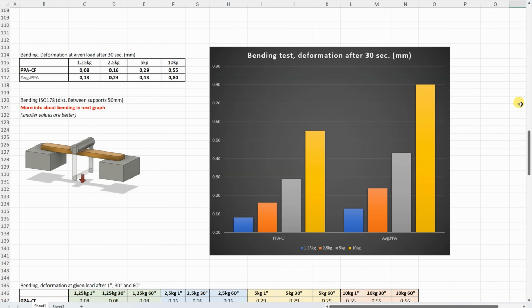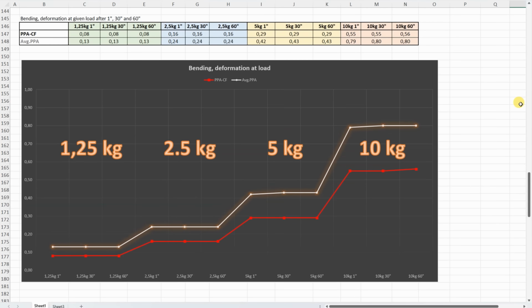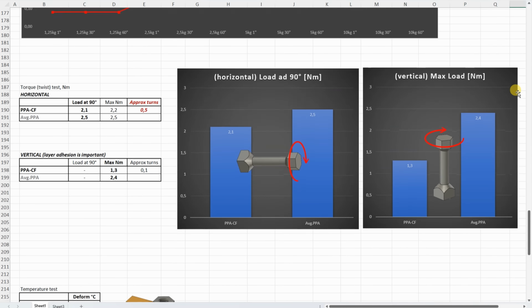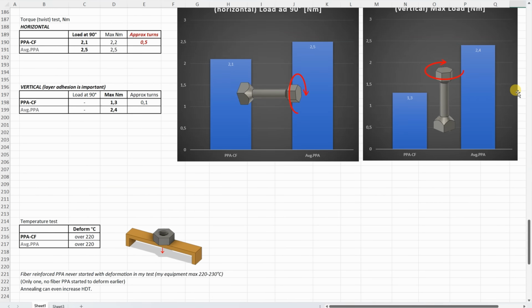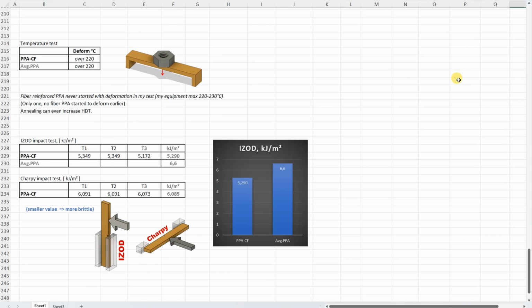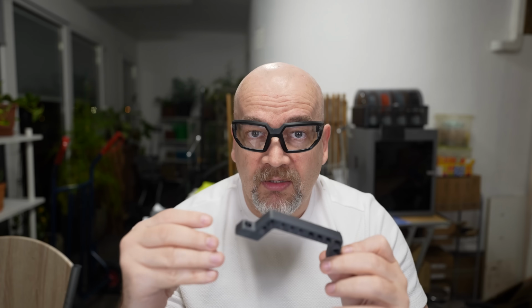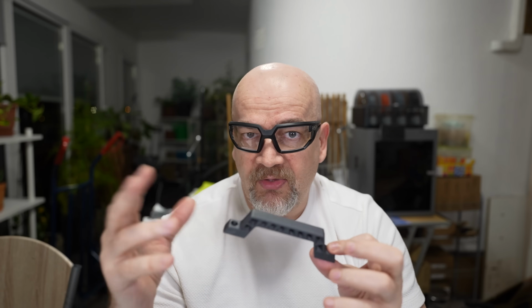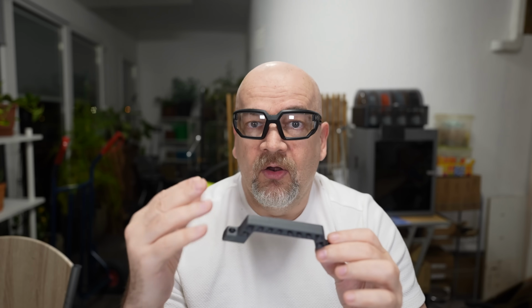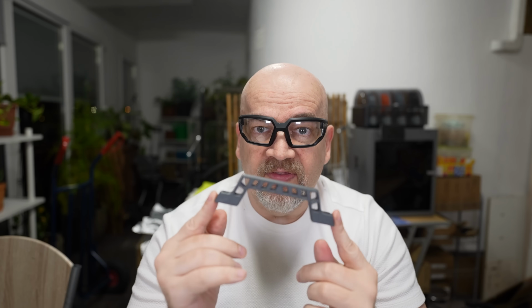Our results one more time: creep test, tensile and layer adhesion, shear test horizontal and vertical, bending deformation after 30 seconds, bending deformation after 1, 30 and 60 seconds, torsion test, temperature and impact test. When I need some really strong part, which resists bending in XY direction with high tensile strength and low creeping, I use PPA-CF.